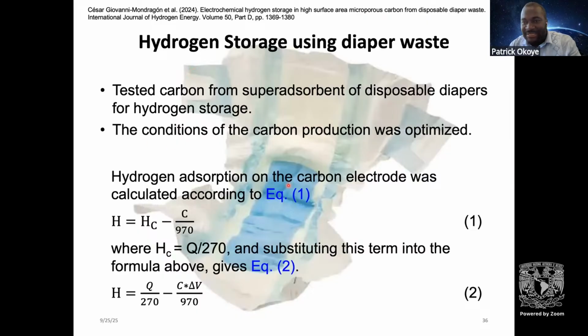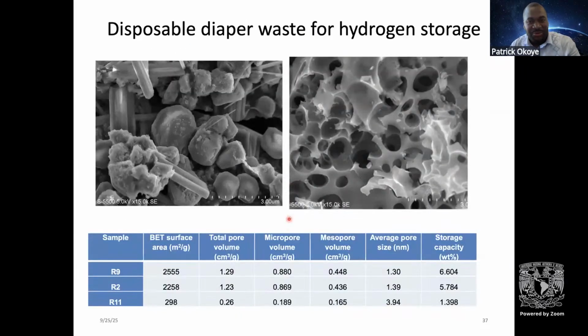So we tested this material for hydrogen storage, and this is the micrograph of just the diaper, and this is the micrograph after we have produced activated carbon. We obtained a significantly high surface area material of 2,555, and we were able to store 6.604.